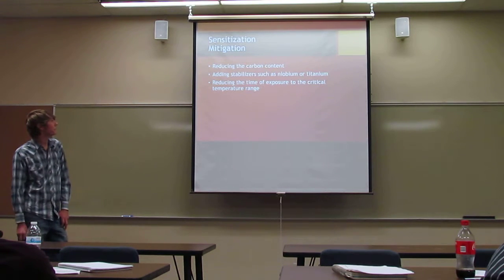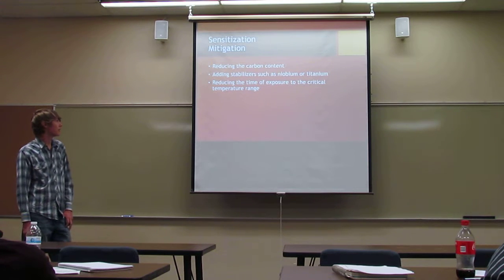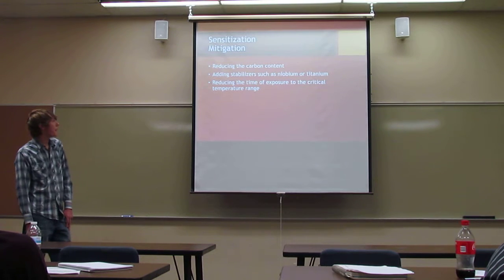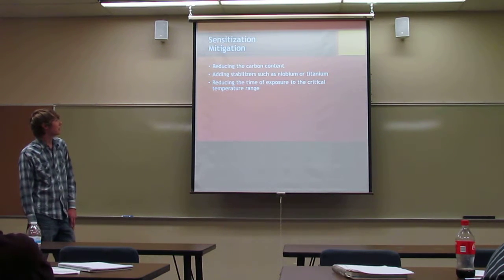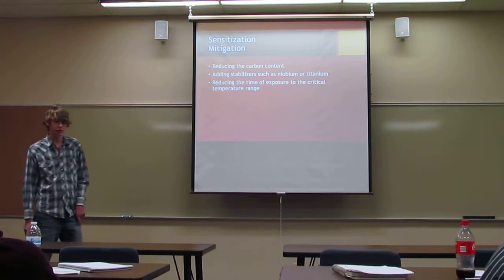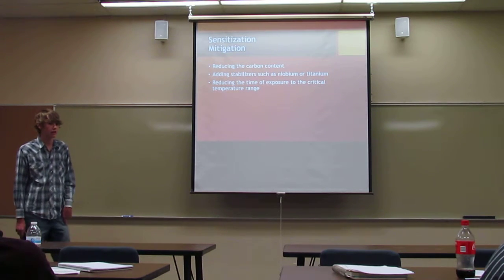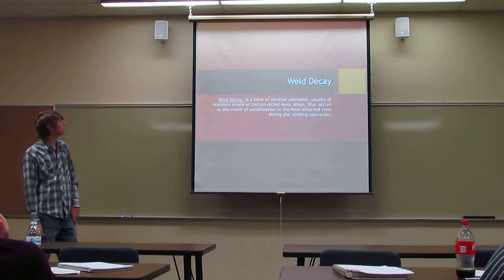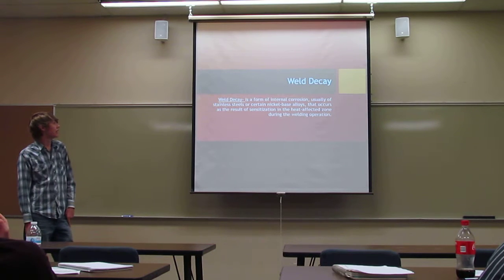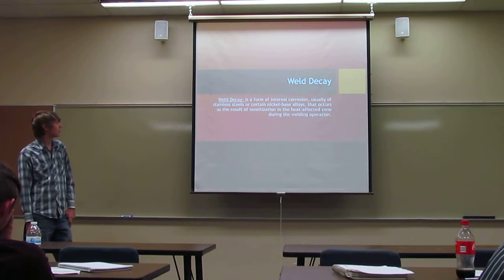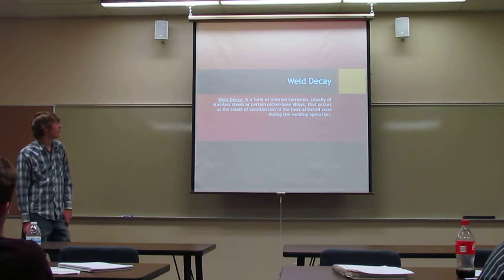The mitigation would be to reduce the carbon content, add stabilizers such as niobium or titanium, and reduce the time of exposure to the critical temperature range, which was 815 degrees Celsius. Weld decay is a form of intergranular corrosion, usually on stainless steels or certain nickel-based alloys, that